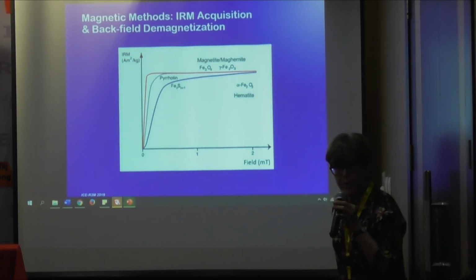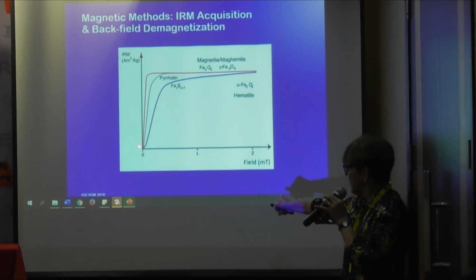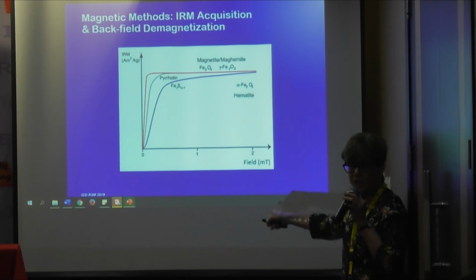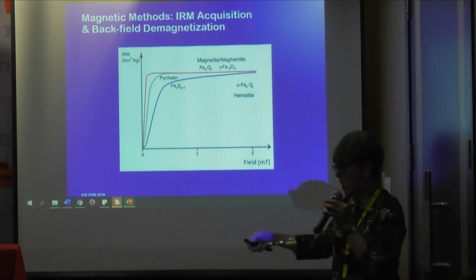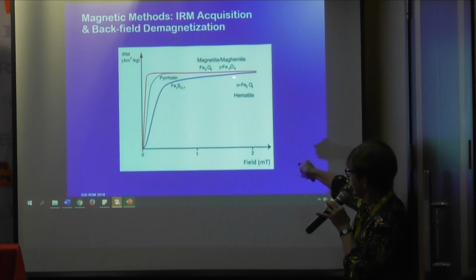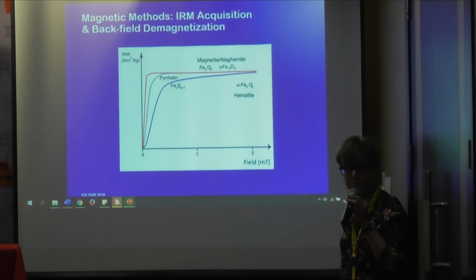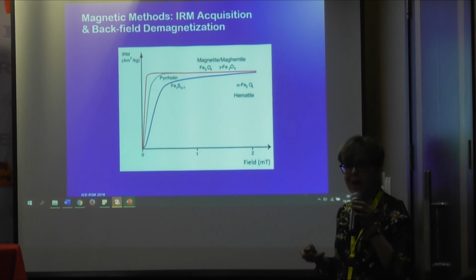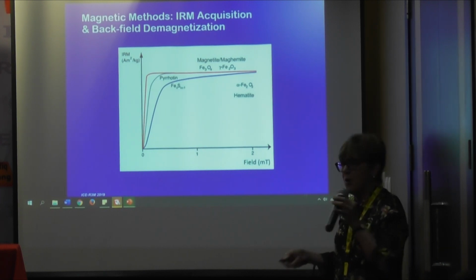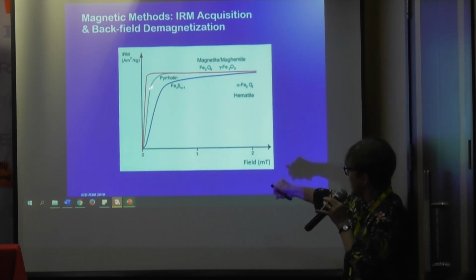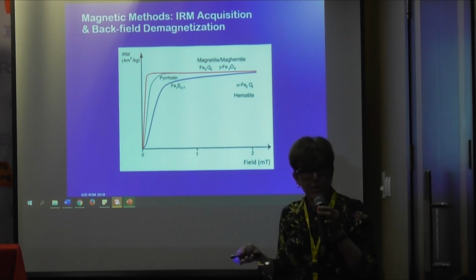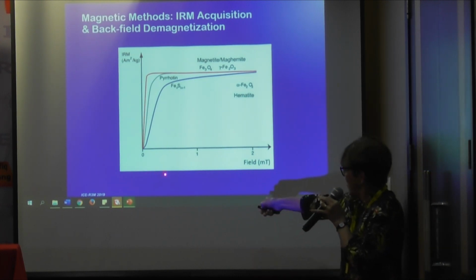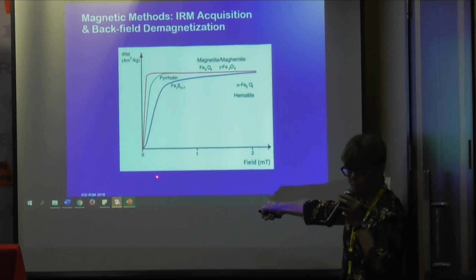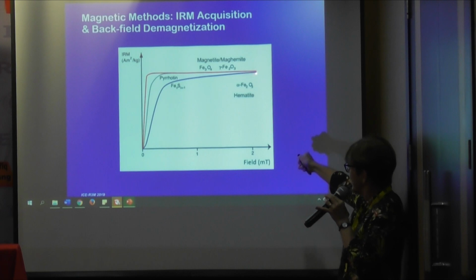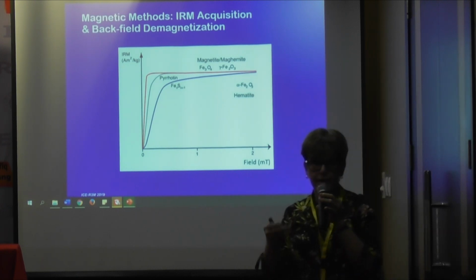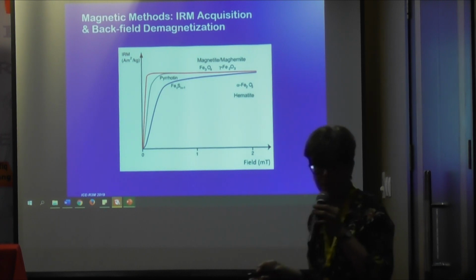Probably you're very familiar with IRM acquisition curves. You can start with a sample, demagnetize it so it has no magnetization, put it in a DC field, and you slowly acquire magnetization. The shape of this is going to tell you something about what material you have. So magnetite, maghemite will acquire magnetization very fast in low fields. Pyrrhotite, I can use the German spelling here, you need a higher field, 500 to 600 millitesla. And with hematite, you'll see it's very hard to magnetize in small fields, but then it'll start to increase. But you need very high fields to saturate it. You usually need 2 to 3 to 4 Tesla in order to saturate the hematite.